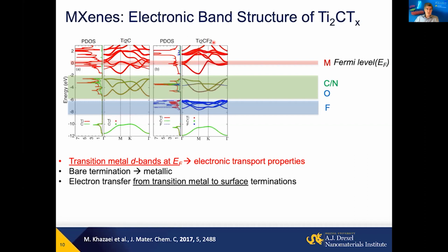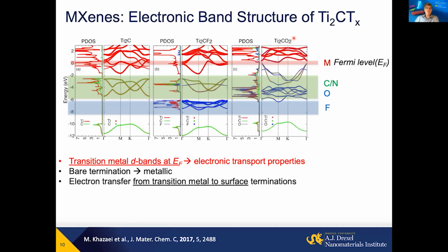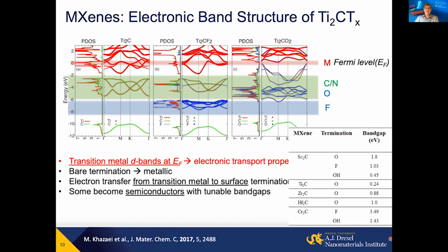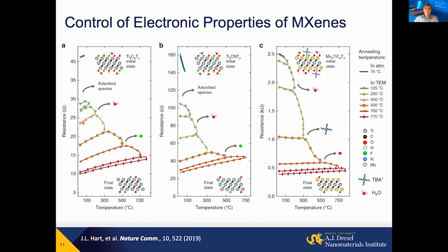The electronic structure changes if it terminates with fluorine. And if you bring oxygen on the surface, which pulls 2 electrons from each titanium atom, it's possible to open a band gap, and actually wider band gaps have been predicted for several other carbides. And we can heat samples of MXene with different surface termination in vacuum, changing their resistivity, and actually sometimes switching